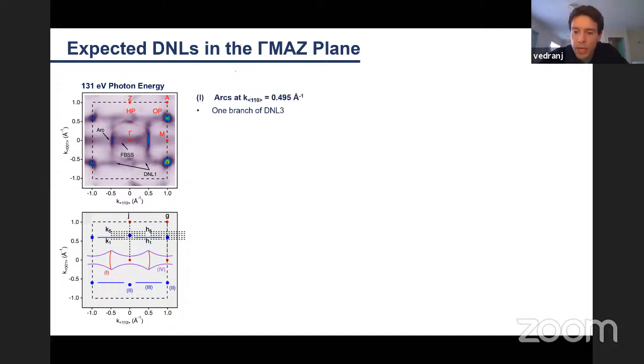So first we identify the arcs, number 1, centered halfway between the ΓM markings. These represent one branch of the Dirac crossing, forming this third Dirac nodal line, which I'll show you later, which was essentially completely missed by theory. Second, we find the intense spectral features at OP along this MA line. These are intersections of the Dirac nodal lines 1 and 2 in the XR momentum plane, and they're complemented by weak features HP along ΓZ, where the Dirac nodal lines cross with one another.